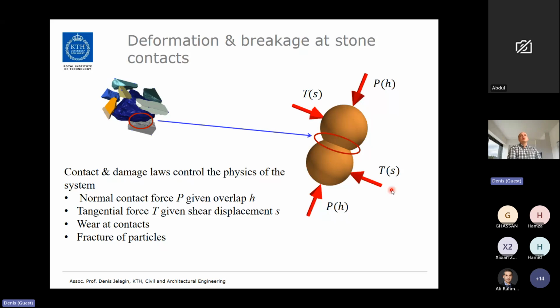In general, there are two schools of thought with respect to contact laws. One school of thought says let's just assume some kind of functional shape of the contact law and then fit parameters from macro scale experiment. Let's do triaxial test on unbound material or simple performance test on asphalt mixture or compaction flow test and adjust contact law parameters until we get agreement with macro scale observation. And that allows a relatively simple procedure. But with this type of approach, it becomes kind of tricky to extrapolate to load levels outside of experimental procedure used to calibrate contact and damage laws.